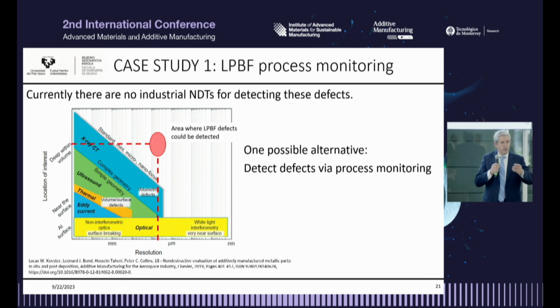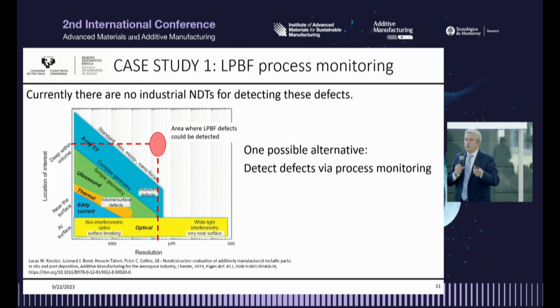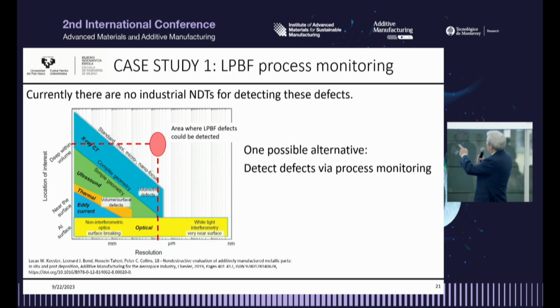But if we go deeper into the part, we have the limit of the X-ray computer tomography, that can go some, let's say, many microns, low millimeters, maybe 2 or 3 millimeters, depending on the density of the part. So the area where we need to detect the defect, this is the red one, and currently we cannot detect them. So another alternative is to detect defects via process monitoring.